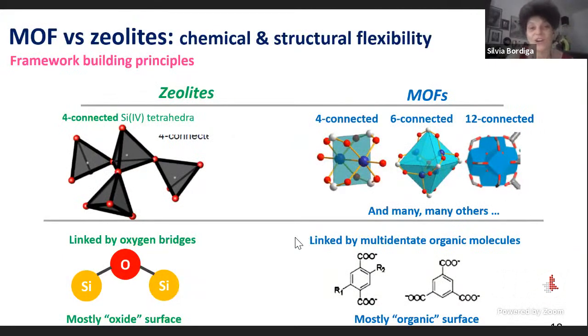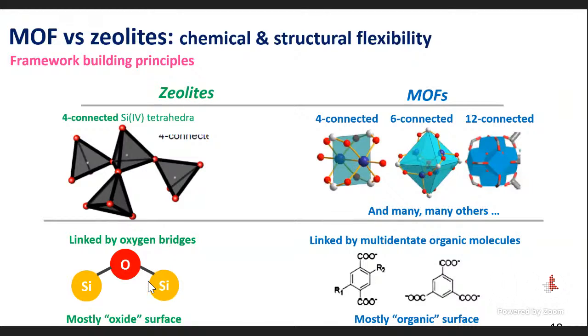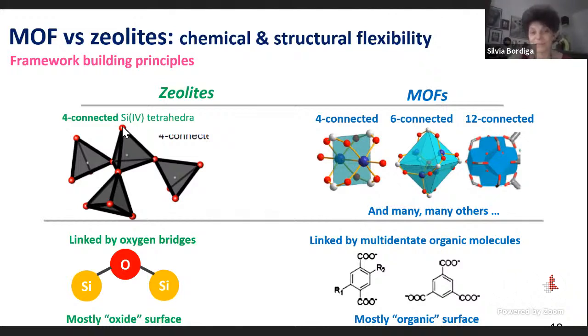So if we compare the building blocks of zeolites and metal organic frameworks, in the case of zeolites, we have the possibility just to play with the angles between the different tetrahedra, and so we have a limited amount of possibilities. Conversely, in the case of MOF, we can play with the different arrangement of the surrounding cations, playing with the specific coordination connection of the different cations used, and the huge variety of the organic linkers, which can have different connections with respect to the cation. And so we can have linkers with, for instance, an arrangement like this one, or with linkers with an arrangement like this one. And so we can end up with a huge variety of structures.